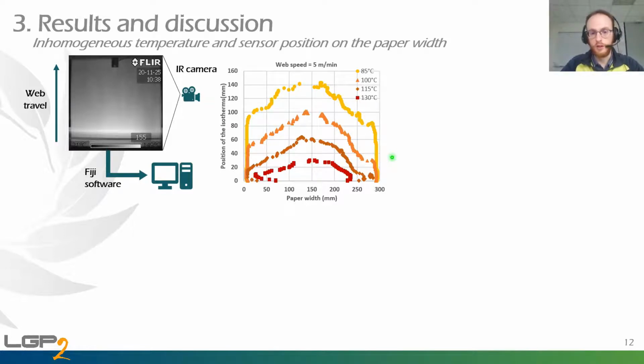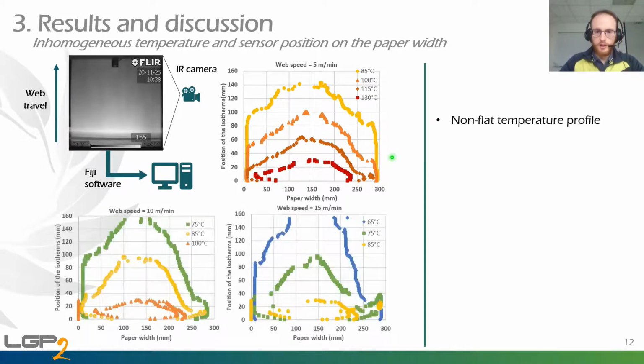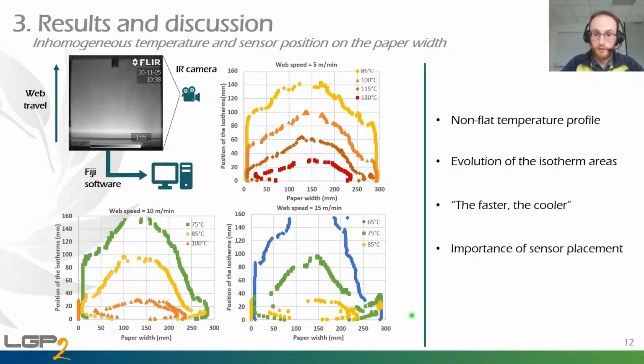First of all, what we can see is that we have a non-flat temperature profile. Now, when we increase the speed from 5 meters per minute to 10 and 15 meters per minute, we can see that we have an evolution of the area covered by isotherms. For example, for the isotherm at 85 Celsius degrees, which starts here and covers a big area, we can see that this area decreases when the speed increases. Moreover, we can also see that the faster, the cooler.